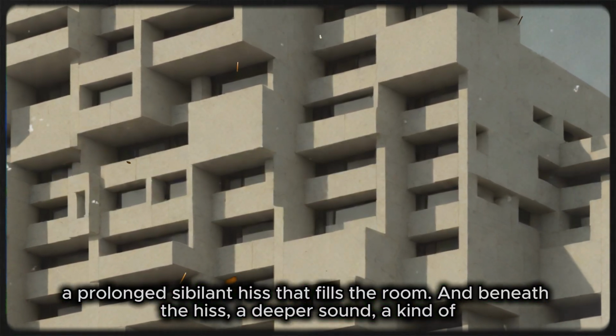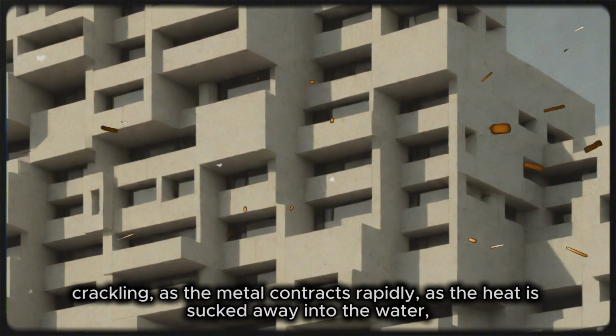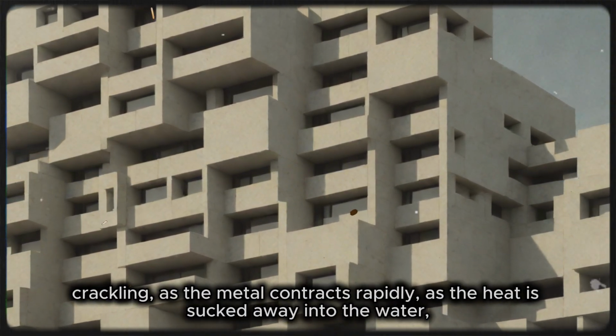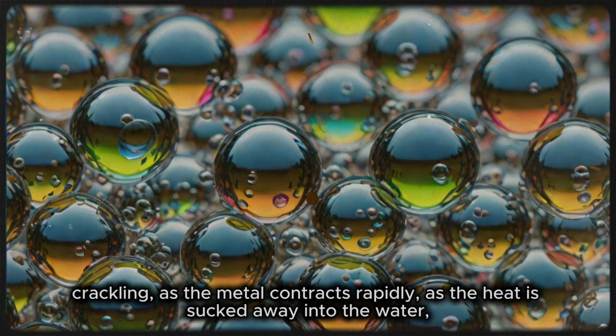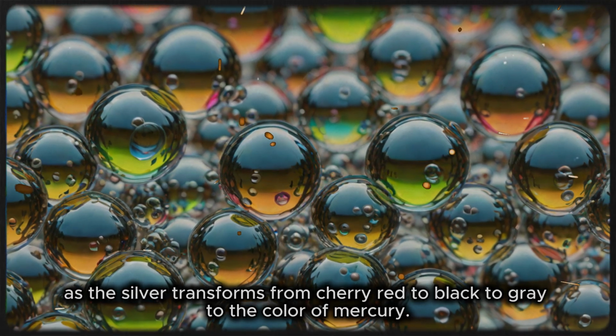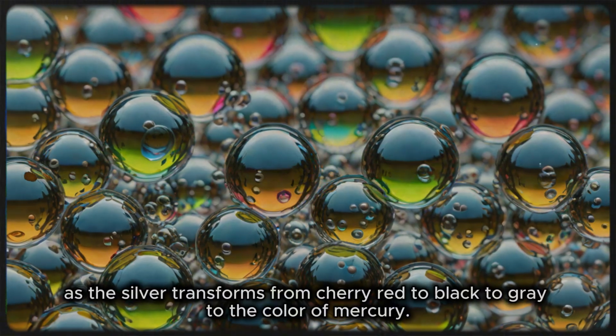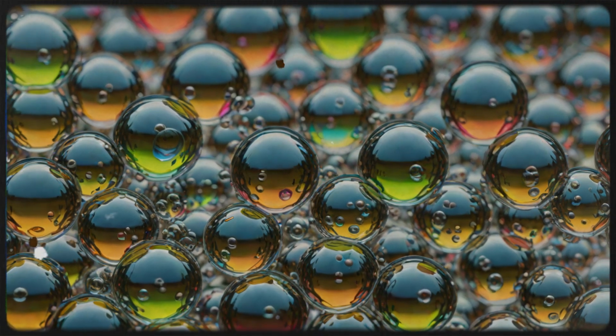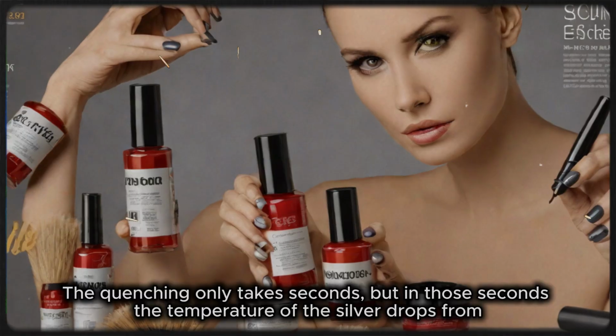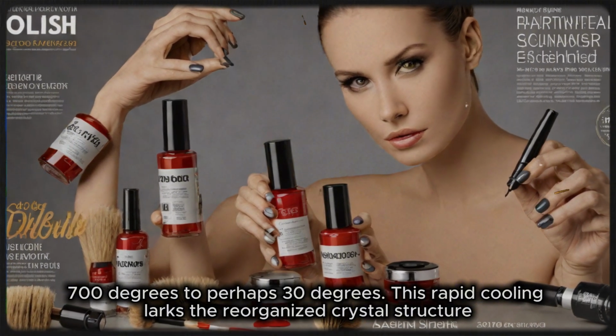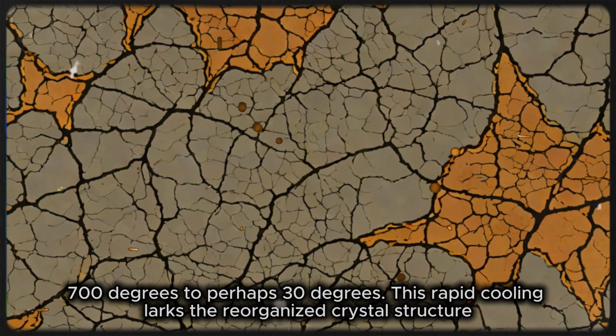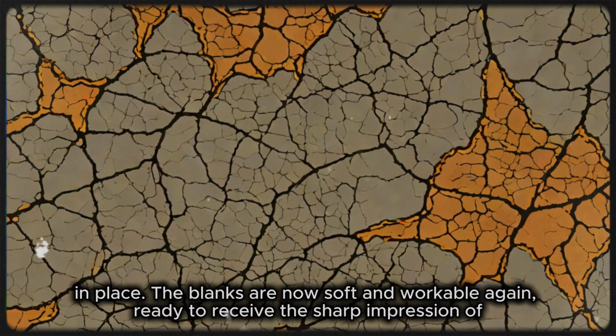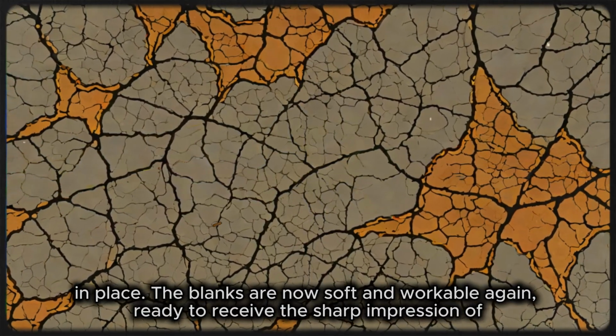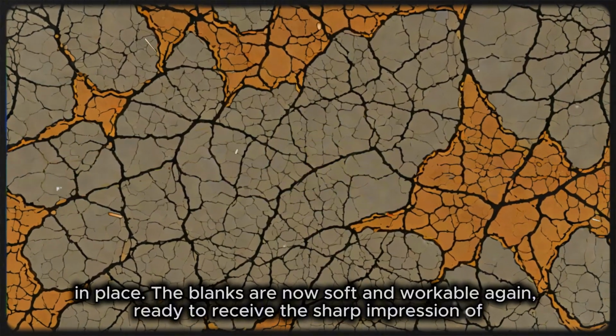And beneath the hiss, a deeper sound, a kind of crackling, as the metal contracts rapidly, as the heat is sucked away into the water, as the silver transforms from cherry red to black to gray to the color of mercury. The quenching only takes seconds. But in those seconds, the temperature of the silver drops from 700 degrees to perhaps 30 degrees. This rapid cooling locks the reorganized crystal structure in place. The blanks are now soft and workable again, ready to receive the sharp impression of the dies.